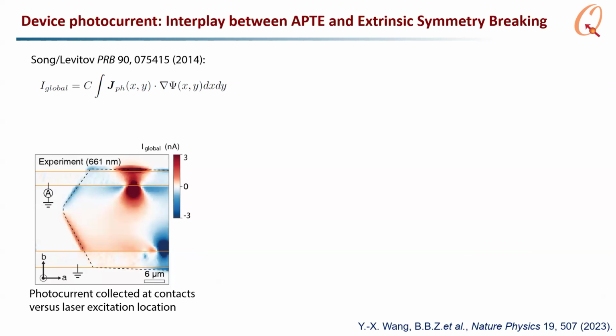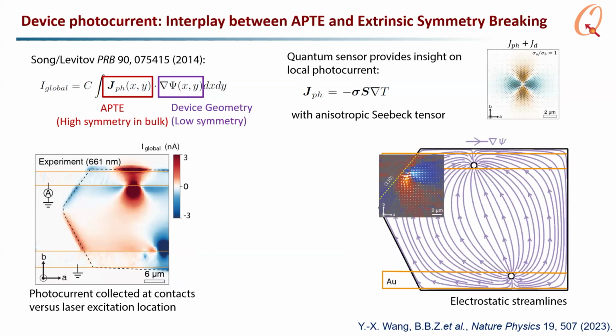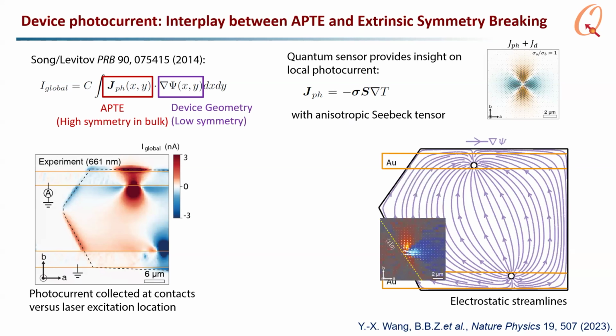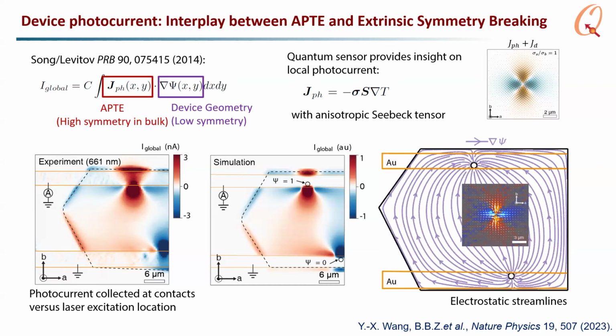By understanding the local photocurrent mechanism, I can show how to design devices to extract that photocurrent. In metals, that's given by the Shockley-Ramo theory, which says it's an interaction between the local photocurrent and essentially your electrostatic streamlines, the electrostatic potential inside the device. So even though the anisotropic photothermoelectric effect has pretty high symmetry, by engineering asymmetry in my device, such as these oblique edges, as well as contact placements that are slightly asymmetric, we can immediately understand the entire photocurrent collected over the entire device.